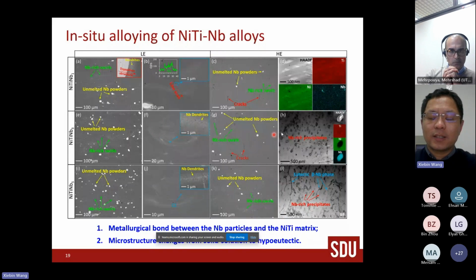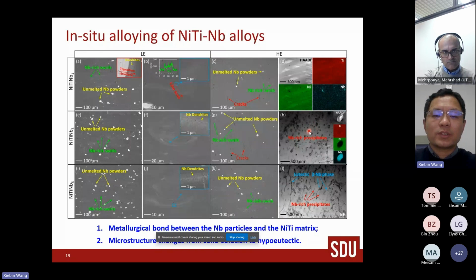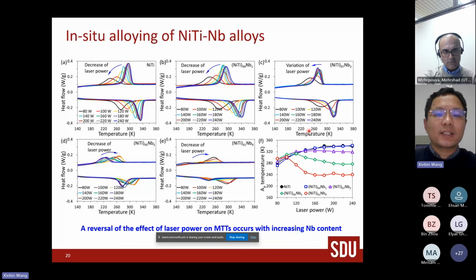Of course, if you look at more details with TEM, there are also some niobium-rich precipitates, and we checked the chemical composition, and it's not pure niobium, it's niobium with some titanium. It's beta niobium particles. And then we check the transformation temperature of these alloys. This result is actually very interesting.